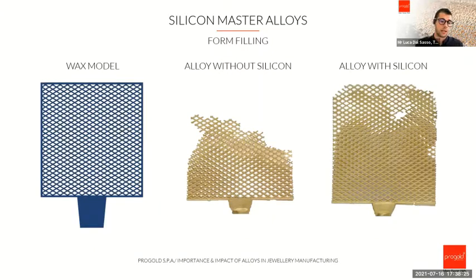Starting from a wax model, like you see on the left, you can see that the quicker solidification doesn't allow the alloy without the silicon to fill all the mold. You can see that in the right one, you have just a few pieces that didn't manage to fill all the mold. So the silicon enlarges this melting range, lowering the solidus, and helps the alloy to stay more liquid and to fill even this mold geometry.